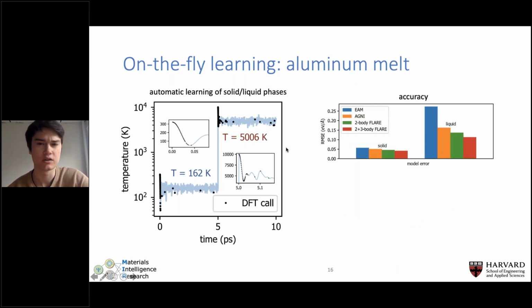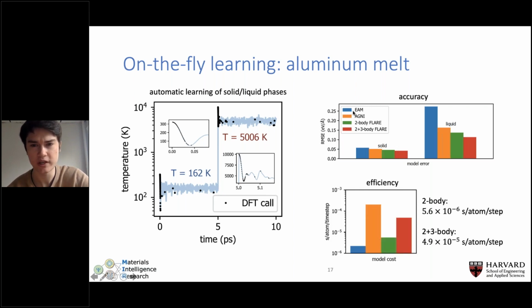And to benchmark how well we're doing relative to a few other aluminum potentials, here we're comparing against an EAM potential, which is one of the faster classical force fields out there, but doesn't necessarily give the best accuracy. And we compare it against another off-the-shelf neural network model. And you can see the errors look quite good.